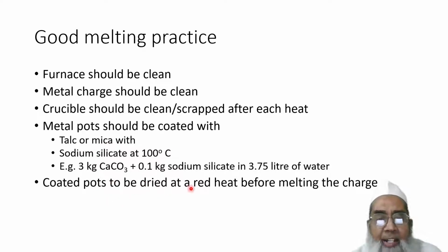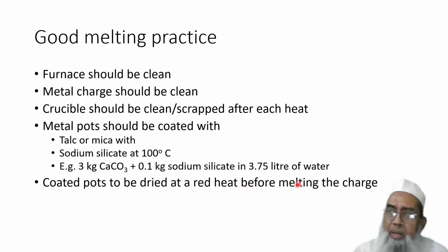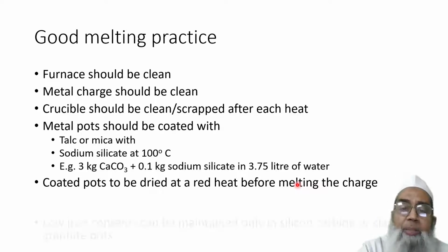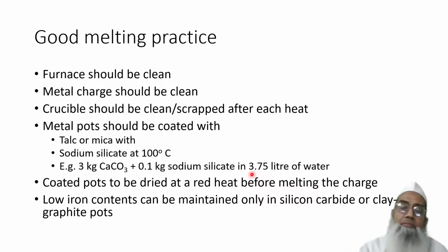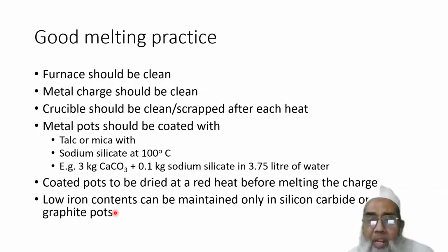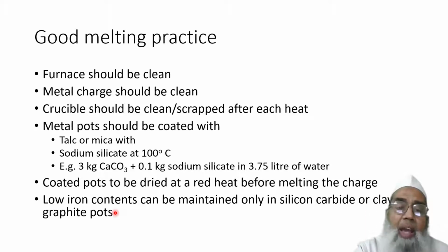Now, coated pots will be dried at a red heat before melting the charge, so that all the volatile material may get evaporated, and the surface of the pot may be free from all contaminations. And low iron content can be maintained only in silicon carbide or clay graphite pots, because iron may be picked up from pots made of steel or cast iron,